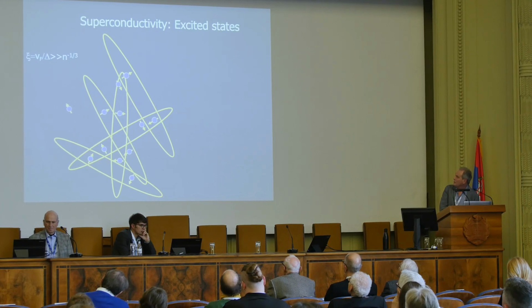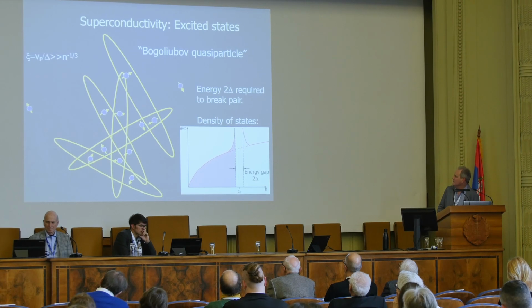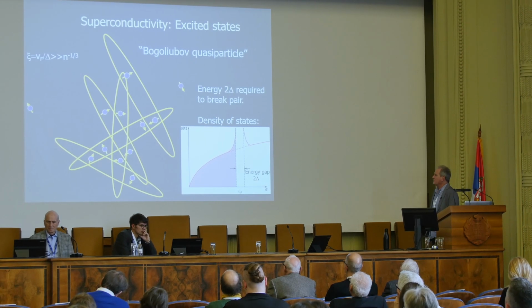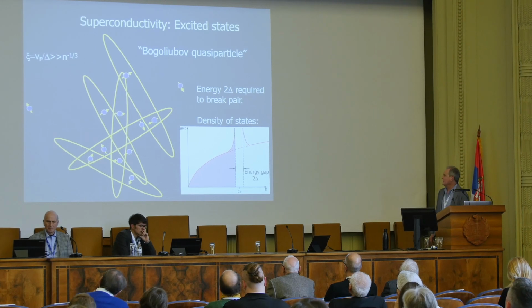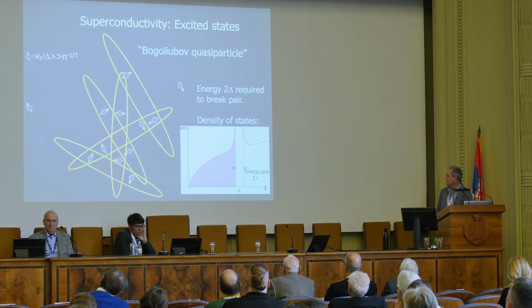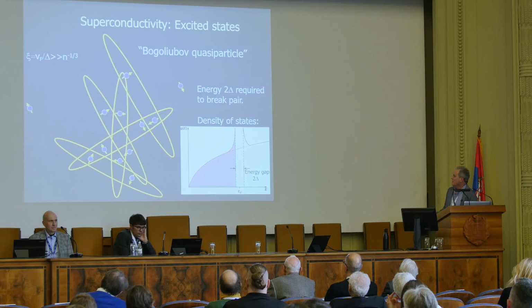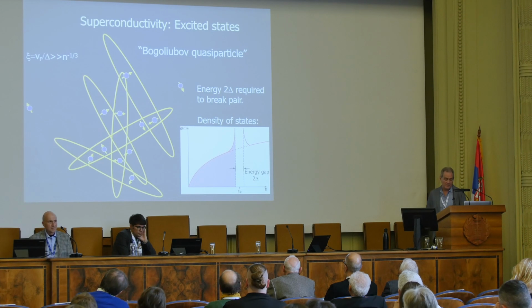So we can make an excited state from the ground state by breaking one of these pairs into two Bogoliubov quasiparticles. Okay, they have their own independent motion, and they can recombine. But the energy it takes to break a pair turns out to be 2 delta, where delta is this anomalous average that I told you about before. And the density of states opens up very close to the actual Fermi level of the normal metal and creates the states pile up nearby.